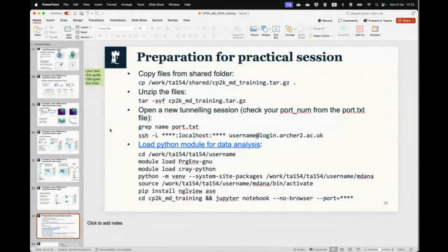Okay. I suggest to use NVT. First, you can try to use NPT to relax the structure, to zero stresses, and after that fix or take the average volume and perform the calculation with NVT. Generally, calculations with NPT are much more difficult than NVT, because you have to control pressure and temperature, and to get pressure to converge you need maybe 100 times longer calculation, because it's generally difficult.